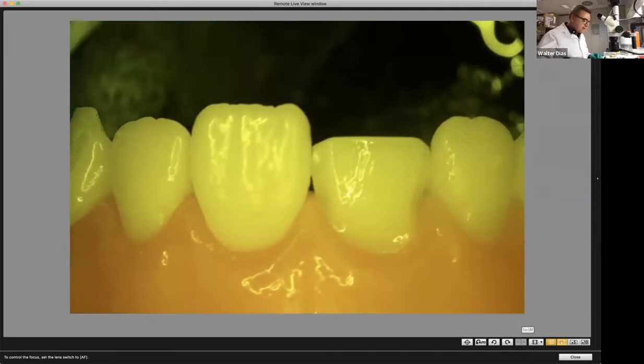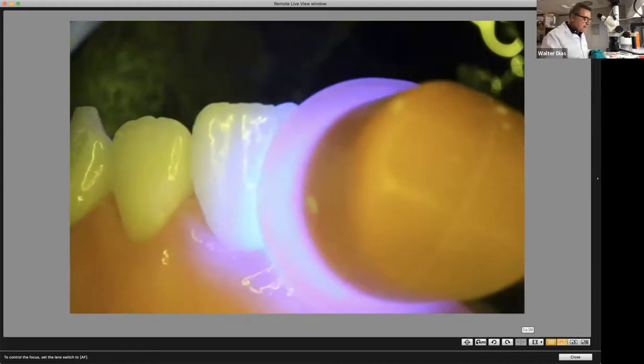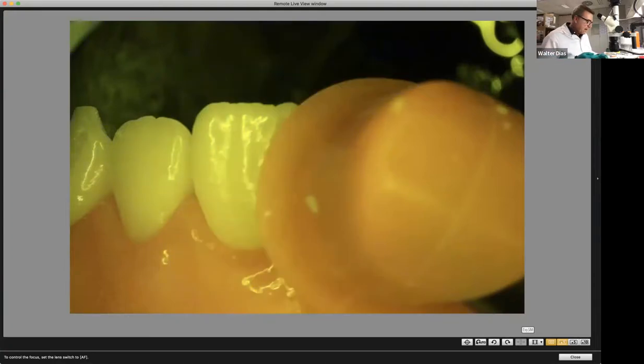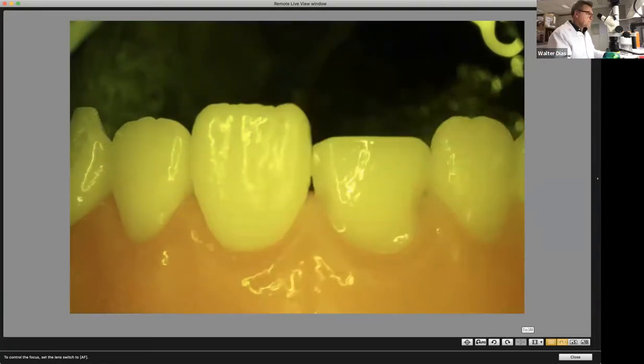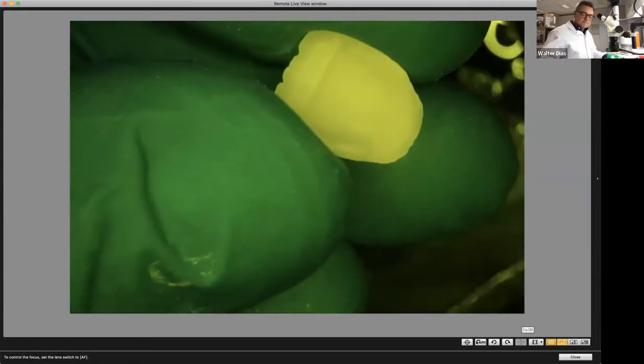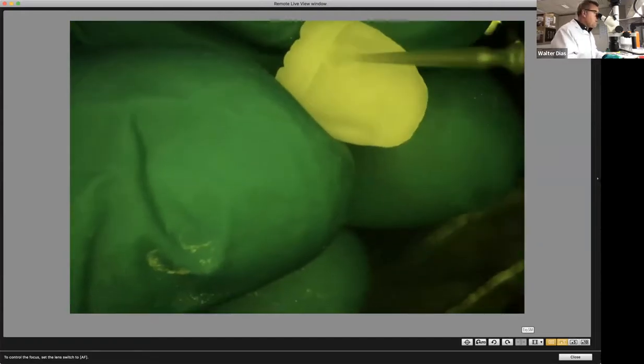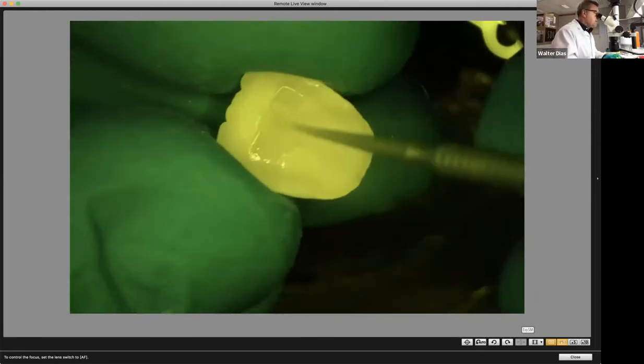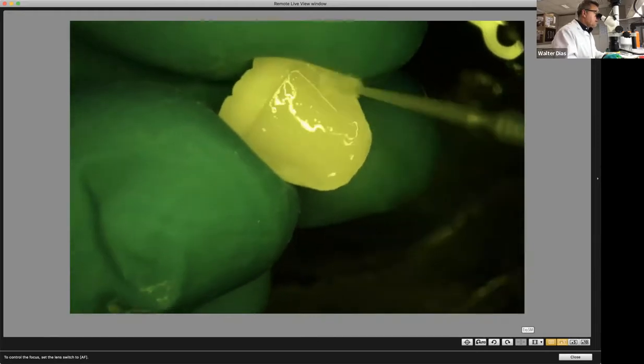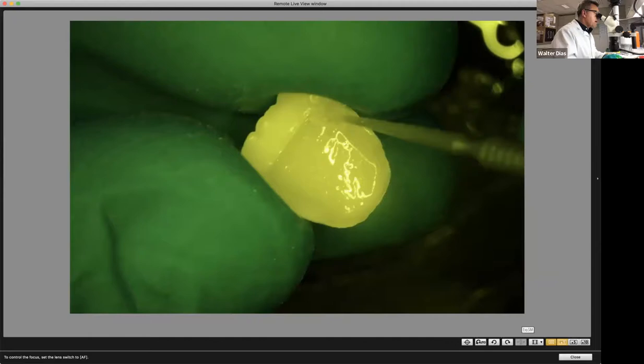You can light cure this for 10 seconds in the front, 10 seconds on the back. At the same time you're doing this, your assistant can be applying the adhesive on the veneer, or you can have already applied this on the veneer. And on the veneer, you don't need to pre-cure the adhesive, because you can cure it through the veneer or through the crown. Up to 4 millimeters of thickness, you can cure through the ceramic crown.